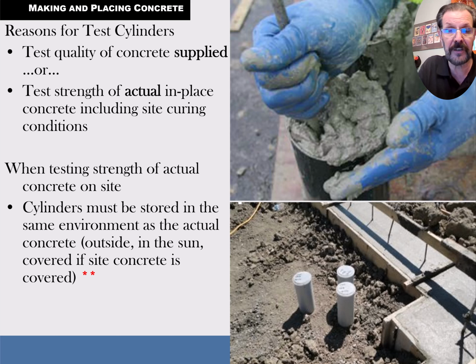This is particularly true on a wall form. When you have a tall wall form on there, as soon as you strip the wall form, that wall will start drying out, and it's hard to continue the moist curing on a concrete wall once you've taken the form loose. With the form on there, it's keeping it moist. It's keeping it from drying out. As soon as you strip those forms, you're going to pretty much lose any additional strength that you're going to get out of that concrete. A lot of the strength will be lost that you could have potentially gotten.